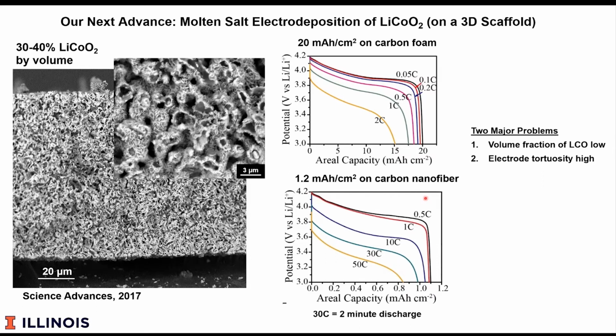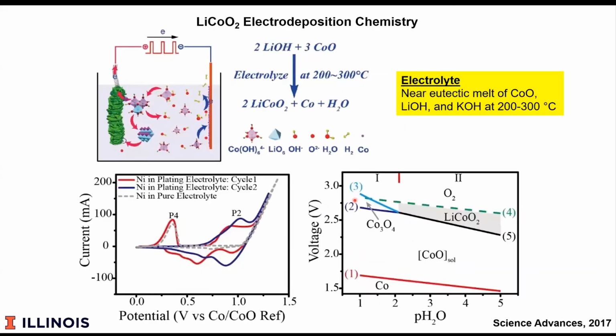And at least when we did it in some circumstances, this is a 10C discharge. So this is a 6-minute discharge. We're still getting something like 80 to 85% of the energy out of the system. But I would argue really what that is, that's cheating. And it's cheating because the volume fraction of LCO is not high enough. But what we did notice as we did this is that we don't have to make it as a foam.